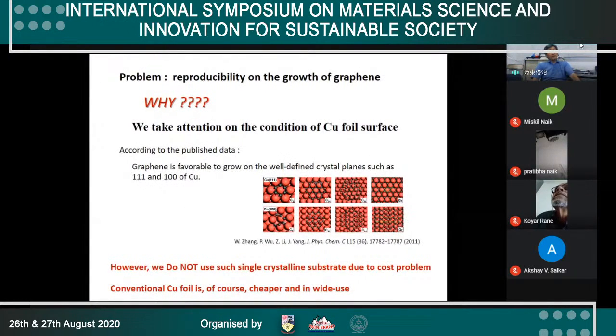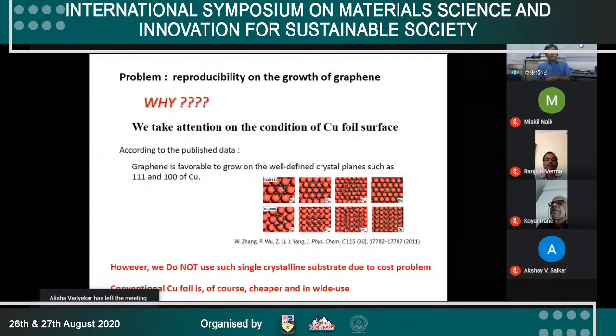So the problem is here. Why? The reason is that we pay attention to the condition of the copper foil surface. Normally, in a lot of publications you can find in the journals, single crystalline copper is normally used. From such research results, graphene is favorable to grow on well-defined crystal planes such as 111 or 100 copper.